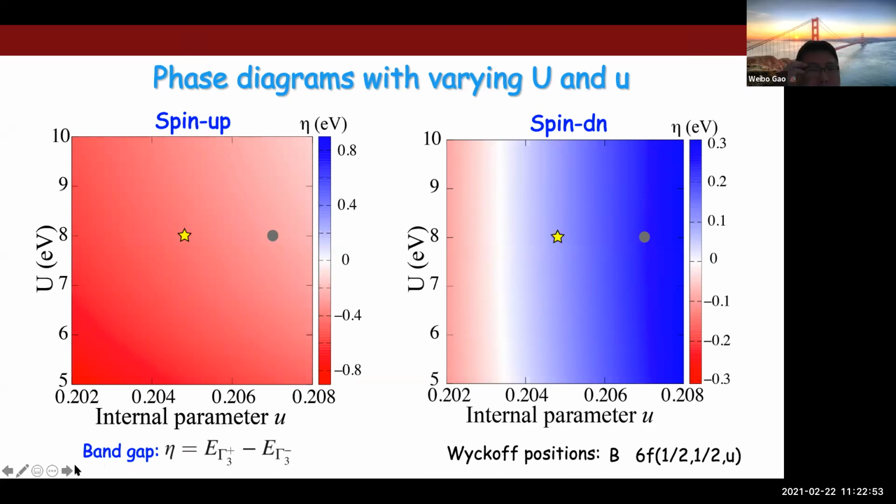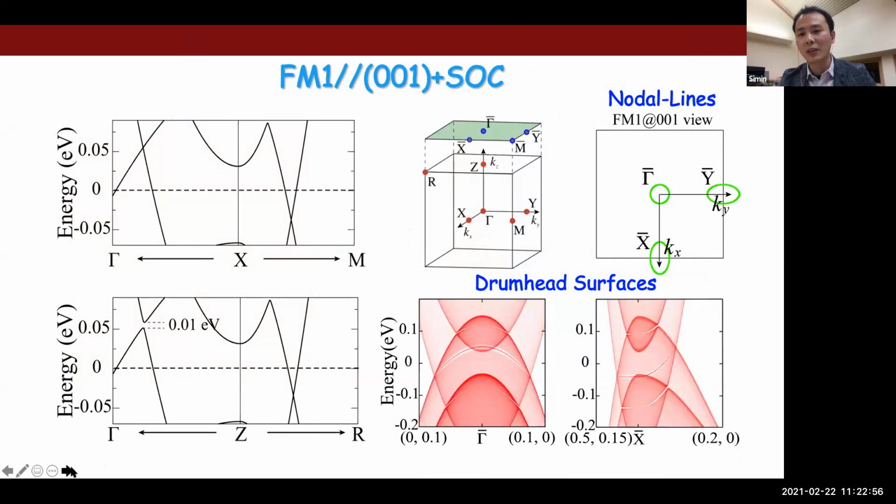Okay, but normally it's much lower than this. Yeah, the temperature is pretty low. Actually, our collaborators found that they must decrease the temperature until 10 Kelvin. There are some magnetic domains in these materials. Only when the temperature is pretty low will the domains become large. That will give you the non-trivial Berry curvature properties.